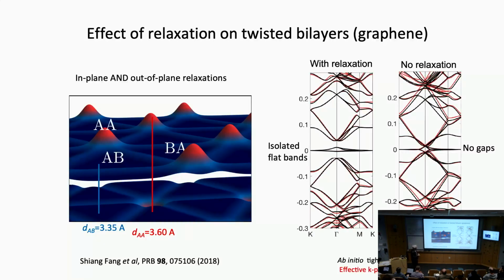So this is the electronic structure with the full relaxation, and this is without relaxation, because since we're doing theory, you can just freeze the atoms in the unrelaxed positions and do the corresponding calculation. So the big difference is the presence of these gaps.